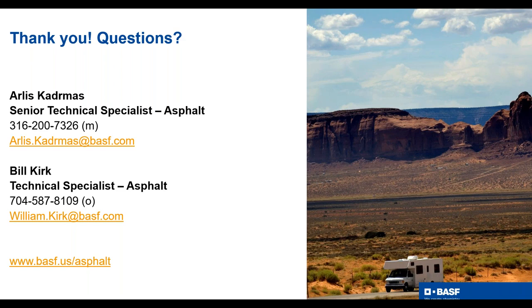They're, like I said, the data's out there that the moisture is pretty much out of the sample and there's no issues with running those residual requirements. But I agree with the comment about the time. There's a process out there, but there are more issues with some of the thinner films now, but people are really looking at trying to develop that a little bit further and get a better process to get that residue. But I think D7497 is a proven method.